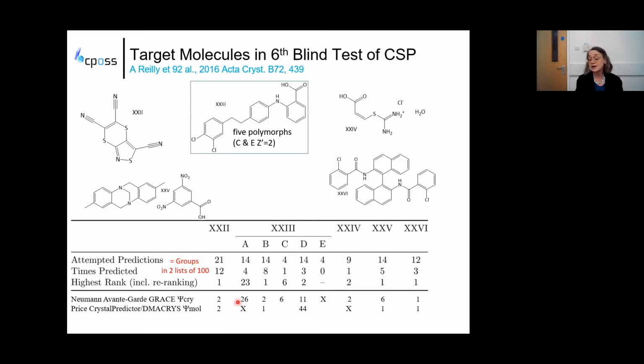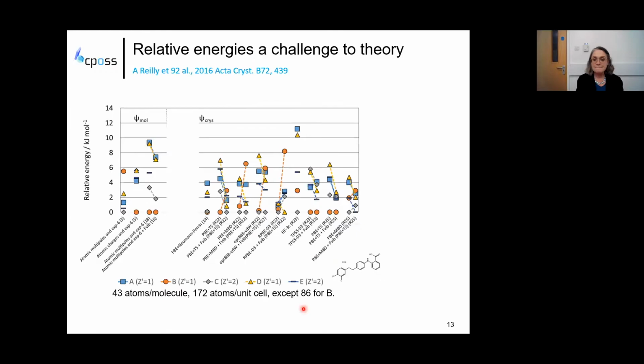And I was very proud because in my group, one person took each target, and the PhD students did very well at applying the methods and getting the things right. We were struggling more with the bigger, more challenging systems. But having 5 polymorphs, and therefore knowing that there's a relative stability and that they exist and should be close in energy, a lot of people tried re-ranking them. And so these are a whole load of different energy models trying to show the relative energies of the 5 different known structures. The dotted lines are when you're trying to put in free energies by a harmonic approximation. And you can see they're all over the shop. We're far from converged on theoretical methods.